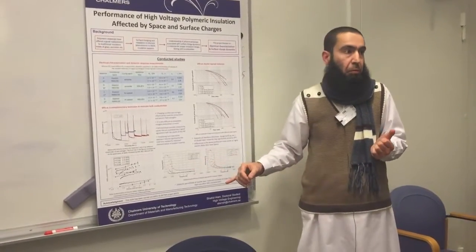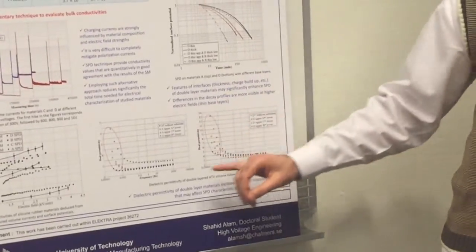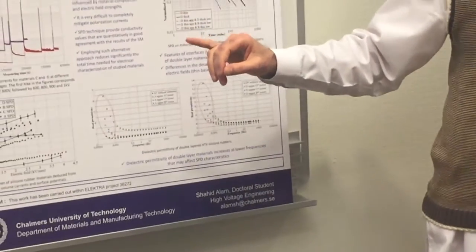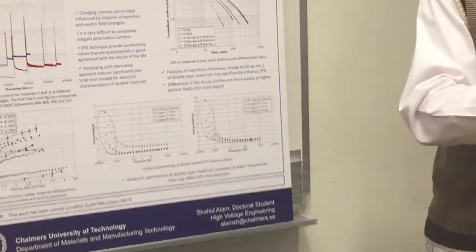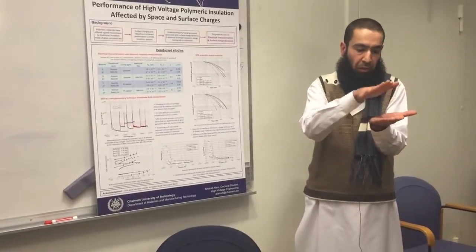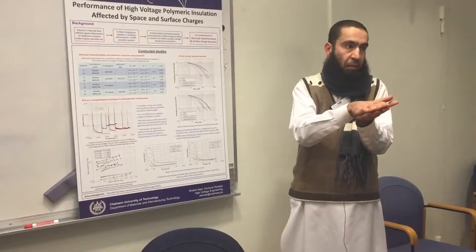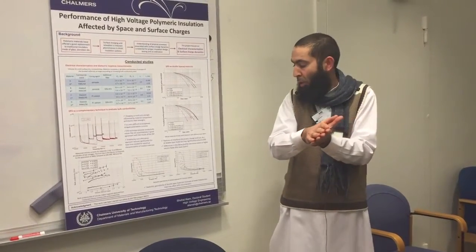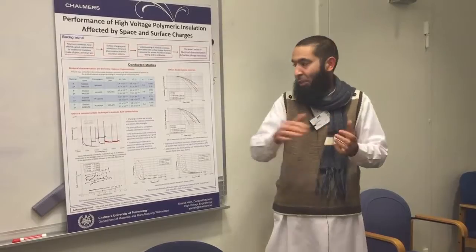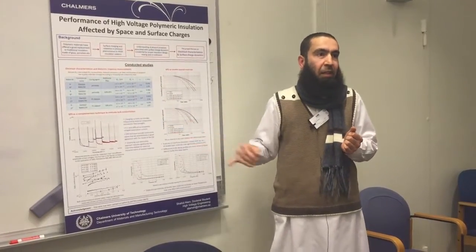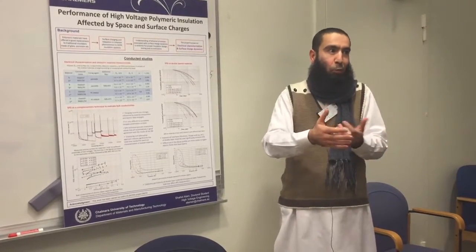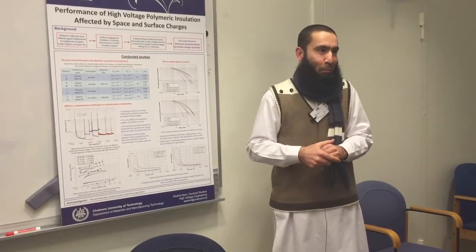And then to complement those measurements, we even did some dielectric spectroscopic measurements, and one can see that at lower frequencies the permittivity increases quite a lot, and that's an indication of interfacial effects, because when the samples are made in a sandwich structure and the charges move along the sample, they get trapped in those regions. And then when we use Maxwell-Wagner, basically because it takes only material properties into account, it does not take into account the traps on the surface of the material, so it doesn't work, and that's what we show by simulations. So that's all I was supposed to say.